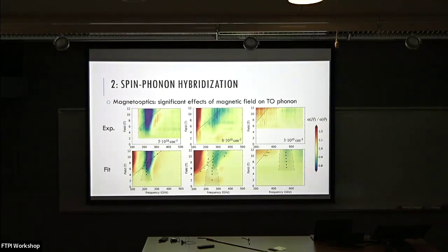So this big blue blob is at frequencies that correspond to this lower TO. And you can see that as the mode frequency shifts in doping, so does the blob. Now at this doping, there's very little left, at least at 12 Tesla. But there is still a little bit. So if you look at individual scans, you can see that something's